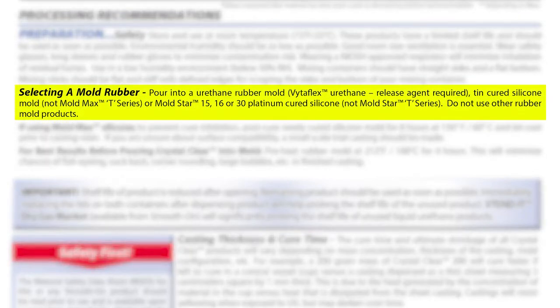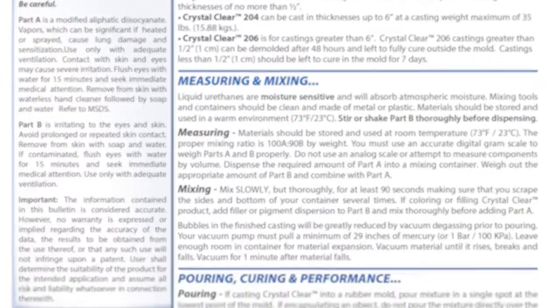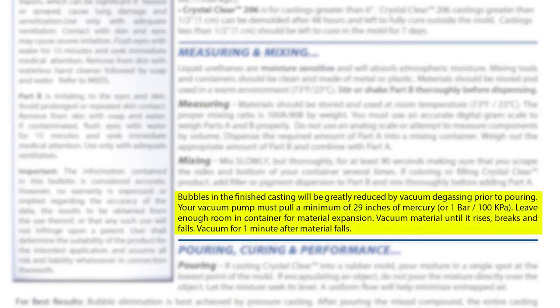When selecting a mold rubber for your project, you should always consult with the technical bulletin. And here you can see that the crystal clear calls for a specific molding rubber. We're going to use a Moldstar 30 glove mold for the crystal clear that we're working with today. You can use a urethane rubber mold. Just remember, you do need to use a release agent, which could potentially change the surface finish and the clarity of our casting. And since we're looking for the best quality in our casting, we're going to vacuum degas as the technical bulletin prescribes to minimize any kinds of air bubbles that are going to be visible in our final product.